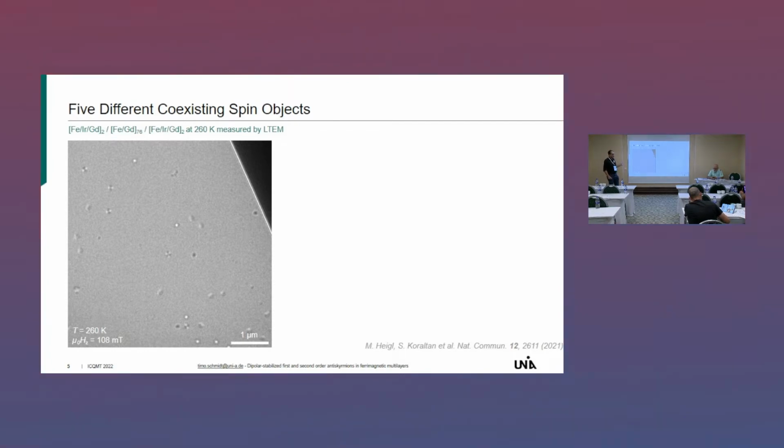One point, all of our samples were sputtered on silicon substrates and also on membranes. So we had the ability to transmit an electron beam through it and do Lorentz microscopy on that. So on that picture, we got a lot of things. So let's start with this one. That is a white dot with a black circumference, and it represents a counterclockwise Bloch skyrmion.